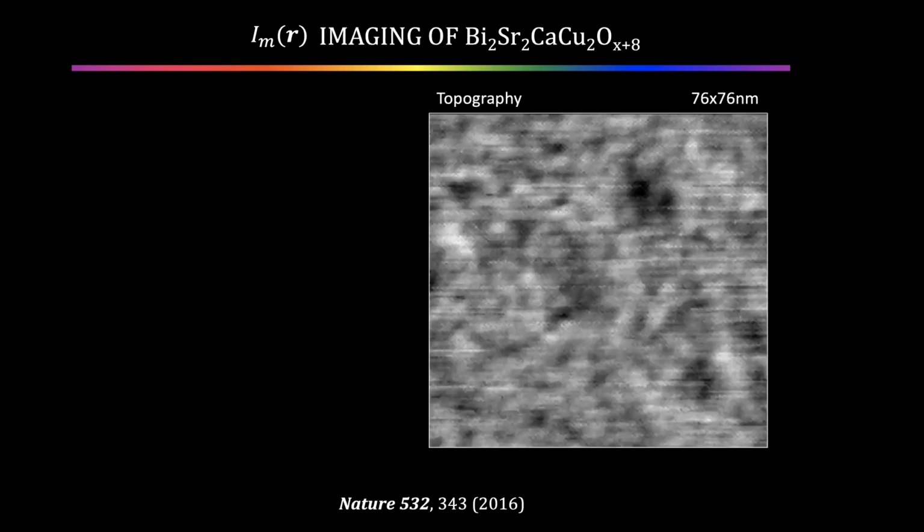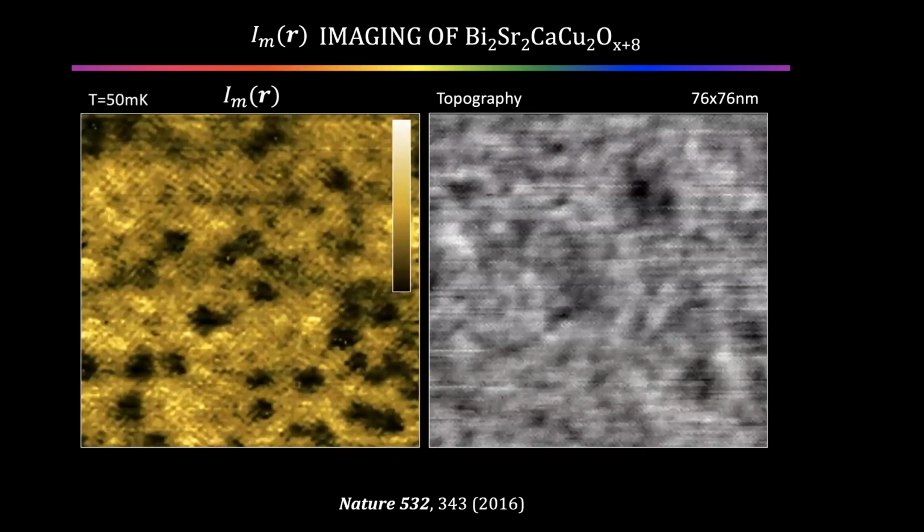So in this field of view, if we measure the maximum in the Josephson current, we see the pair condensate of the cuprates. I think this probably was the first image ever made of the pair condensate in the cuprates. And it has a whole bunch of interesting things. These holes in the order parameter are there deliberately. We put zinc atoms in the crystal so we could calibrate whether the machine is working or not, because zinc destroys the condensate. But if you look elsewhere, you can see there is a modulation.